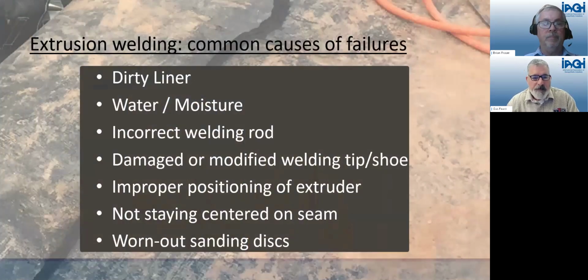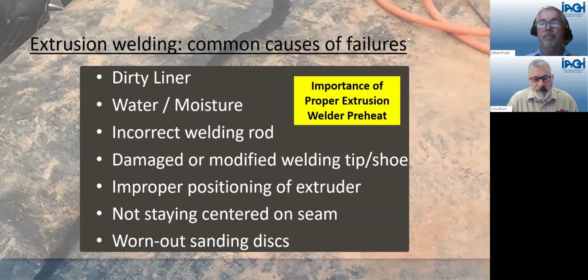Next slide, please. Extrusion welding, common causes of failures in the field. Of course, dirty liner is no good. Water and moisture, plastic welding does not like water, does not like moisture. Improper welding rod, make sure you have the proper welding rod for the material you're installing. Damaged or modified welding tip or welding shoe, it's very important. Improper positioning of the extruder is also very important. Not staying centered on the seam is also very important. Proper grinding disc and worn out grinding discs are very problematic. And also don't forget to make sure that your preheat blower is on and at the proper temperature according to what thickness of material you're welding in the field.